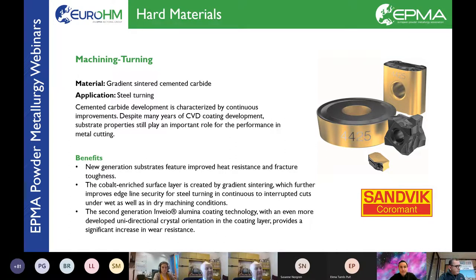So just a simple comment here, and now this example, I think it's one of the clear examples where microstructure is playing a role in the application, and connecting also to what we mentioned before, one of the reasons we use these gradient sintered carbides is because usually in cemented carbides we need to combine hardness and toughness, and in some applications we need more toughness than the material can give us. For this, we are creating this kind of grain structure where we locally are changing the properties of the cemented carbide. And this is a very fascinating microstructure because the modification of the microstructure locally in the cemented carbide is produced by diffusion, in a diffusion control process in sintering.